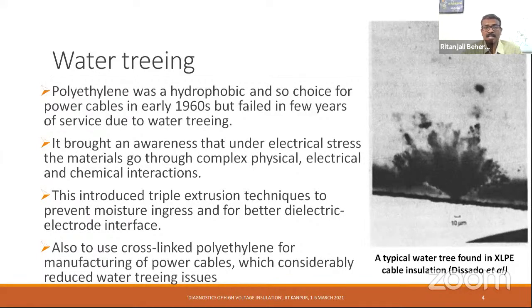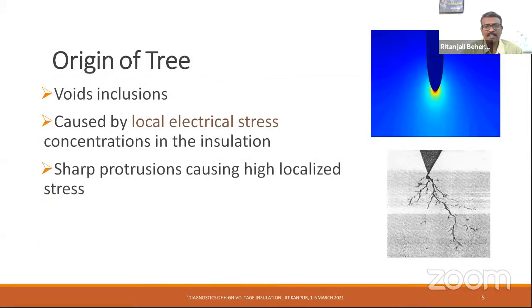Also, cross-linked polyethylene was developed in order to manufacture power cables. This had considerably reduced the water treeing issues. Origin of tree: there can be void inclusions. Even with the high manufacturing techniques, there are still void inclusions present, and there are protrusions in the manufactured cables and the insulation.